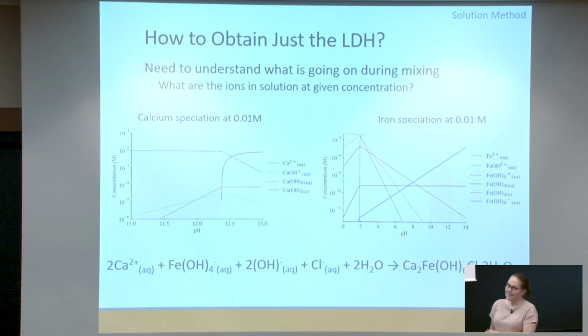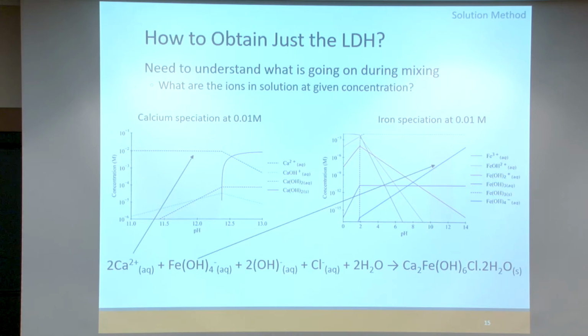So what happens? This is the chemical equation that people have shown in the past. We look at the dominant species in solution that come together to form this layered double hydroxide, and that's why we're in these regions of these speciation diagrams. The calcium 2+ is the main ion in solution here. This is a tetrahydroxide ion, which is the main solution species around this pH. And then you've got the other aqueous ions that come together.